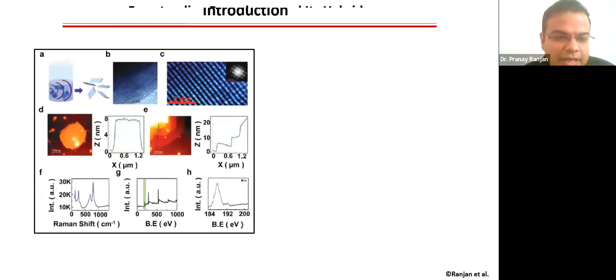So after all these hypotheses, I came up with my technique where I tried to exfoliate borophene through sonochemical exfoliation. So I tried to optimize the solvent energy and the material phases, and then tried to exfoliate through different sonochemical times as well as frequencies. Indeed, different characterization techniques, including Raman and XPS, were used just to confirm that the material has been made in the right phase and purity.